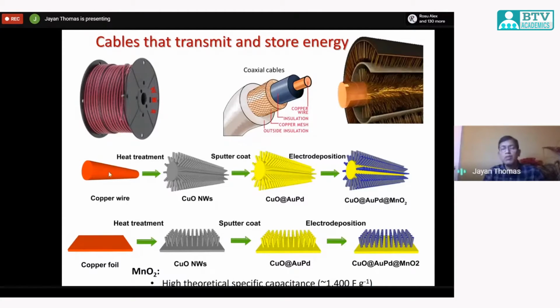It's a very simple technique. We used the copper wire, and by heating the copper wire, you can convert that copper wire into copper oxide nanowires. Copper oxide is an insulating material, so you may need another conducting material on top of it to make it into an electrode. So we deposited another material like gold palladium. There is nothing special about that gold palladium; you can use copper as well. So we electrochemically deposited an active material on these nanowires, and now this is an active electrode itself.